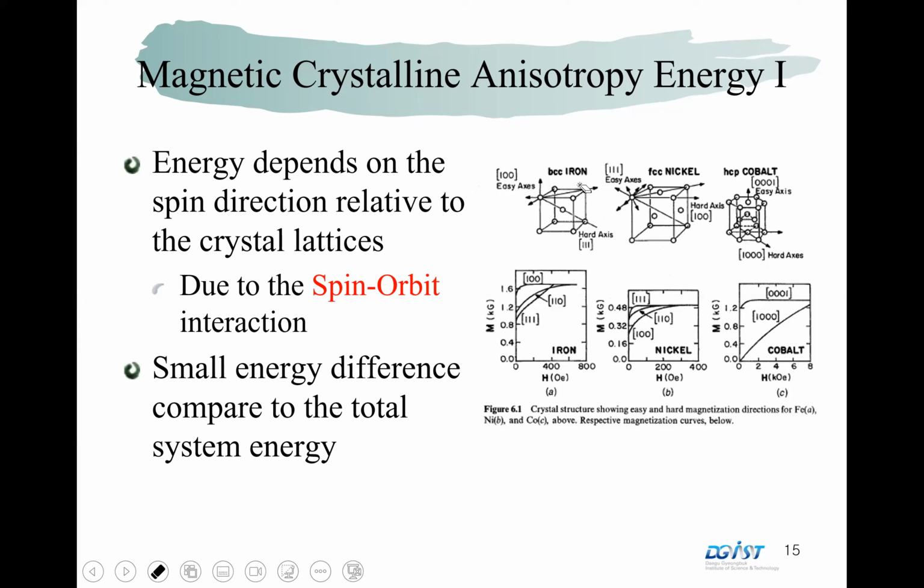So in polycrystal films, actually when we grow the films by sputtering, they usually form a polycrystal. So in that case, in the in-plane direction, there is some chance of crystal anisotropy, but usually they are going to cancel out each other. But still, they have a chance to have a preferred orientation in the films.